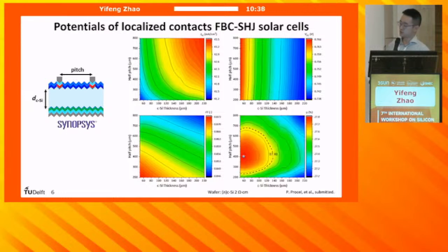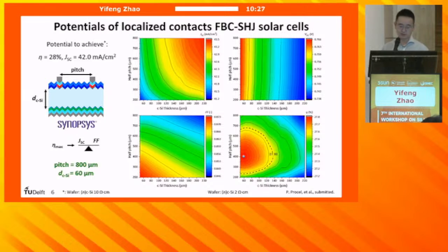And eventually, for the maximum efficiency, there is a careful trade-off of the JSC and fill factor, and the optimum pitch we calculated is 800 micrometer, and the thickness of 60 micrometer. By further optimizing the wafer resistivity to 10 ohm centimeter, we can achieve a calculated efficiency of 28% and with a JSC of 42 milliampere per square centimeter. And this is close to what IBC cells can achieve.